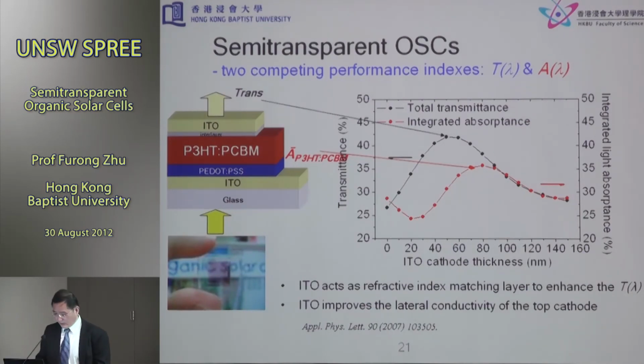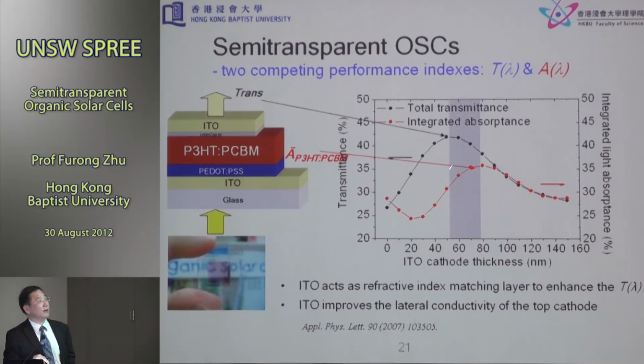So it tends to agree that if we only select the ITO thickness according to the maximum absorbance, then you won't get very good transparency. So in order to optimize both, in actual applications we probably need to take care of both. So long as you select the layer thickness in these agreeable regions, you probably get a device with both high transparency and high absorbance. Anything away from this, you either lose the transparency or you lose the absorbance. So this is how it is selected.